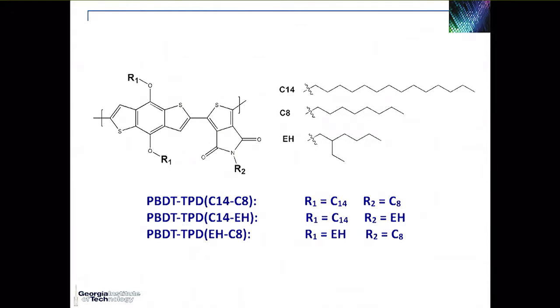Pierre Beaujuge synthesized, with the same backbone, a number of copolymers that had variations in their side chains. So either all the side chains, R1 and R2, being just straight alkyl chains, or in another instance, having normal alkyl chains on the electron donor part, the electron-rich part, and a branched ethylhexyl chain on the electron-poor part, or vice versa.